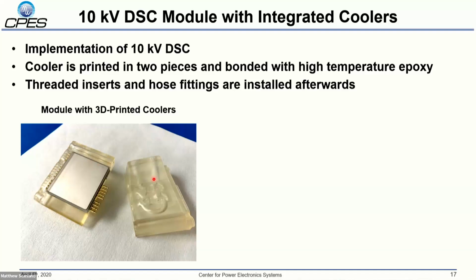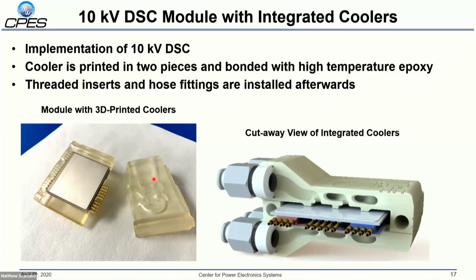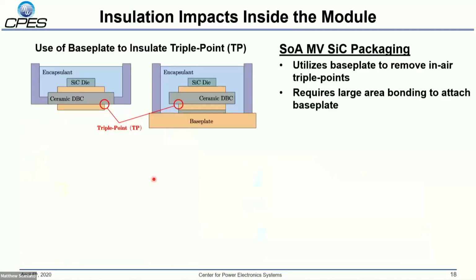And in my experience, the epoxy bond on this 3D printed material is actually stronger than the bulk 3D printed material itself. So it effectively acts as a one-piece housing after it's assembled. And here you can see a cross-sectional view of these cooling channels that are printed into the housing, and how these jets are able to impinge directly on that substrate and give us that direct substrate cooling.